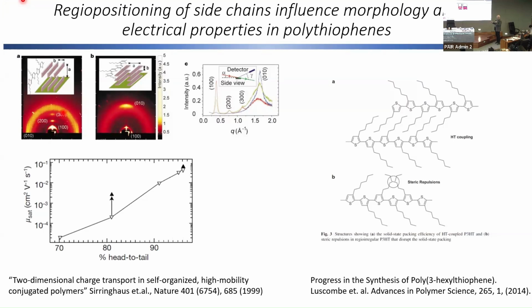And it's when we get the edge on orientation, we get this out-of-plane reflection in the lamella, this 100, 200, 300. That's the d-spacing between, if you like, the sandwich layers of this structure. So it's a very nicely lamellar structure. And when we have this, then the carrier mobility, this figure of merit I described earlier, goes up now to about 10 to the minus 1 centimeter squared per volt second, whereas this material that has a lower regioregularity has a much lower charge carrier mobility. So if we're trying to squeeze every little piece of performance out of our device, we want to go with the very high charge carrier mobility materials. That makes a big difference.